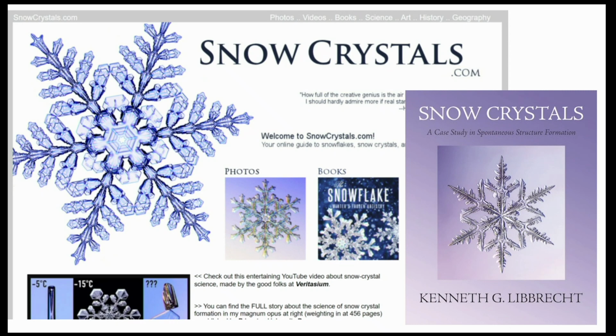Well, we make two-dimensional cylindrically symmetric models because they're easier than 3D models by a lot, of course. But no, the kinetics is highly anisotropic. And the surface tension in ice is very nearly isotropic, so close to isotropic that we can ignore anisotropy. But the attachment kinetics is just wildly anisotropic. So it's very important.